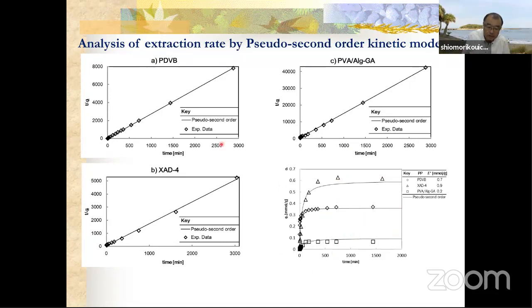But I think this second order kinetic model is quite a rough analysis. So now we try a more detailed analysis by the two extraction steps. One is a chemical reaction at the interface, and the second one is diffusion of the extractant or extraction complex in the pore of the particle. So we analyze two different stages of the extraction step.